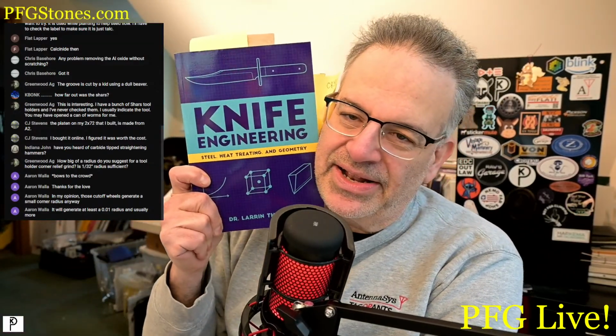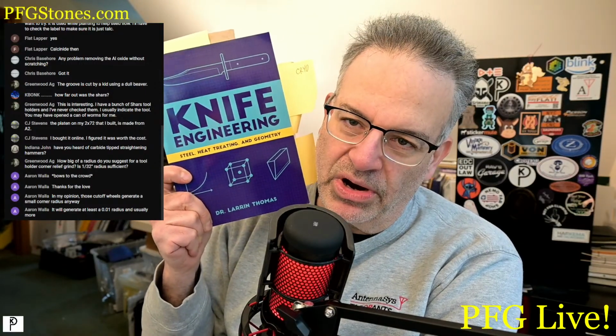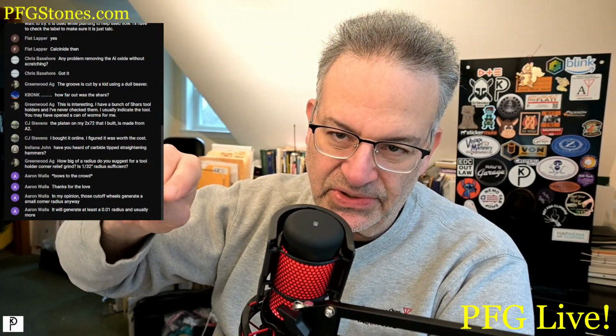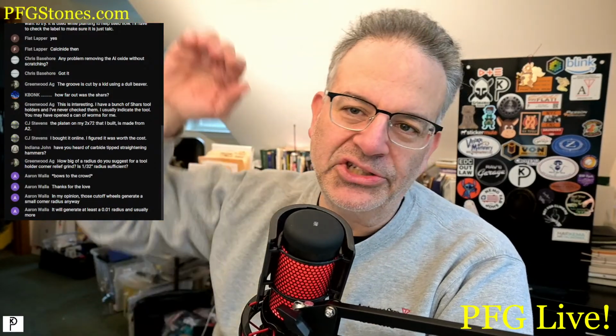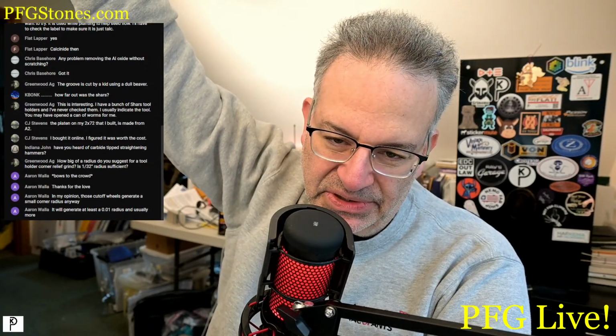Larrin Thomas says, yeah, as soon as you're able to get that quenched part into cryo, do it. You have 1 hour to get that thing finished being quenched. So I completely went against Mr. Bryson. I did what Dr. Thomas told me, and it came out great. We air quenched until I was able to touch the parts, and then they went into the liquid nitrogen, and they went all the way down. So the quench effectively went from the high temperature, which was 1775, continuously down to minus 300 or whatever liquid nitrogen is. Yeah, Aaron says that the cutoff wheel will generate at least 10 thousandths radius and usually more, and that's enough to prevent a stress riser, which we're really worried about. Although I did touch it up a little bit and make it a little juicier.